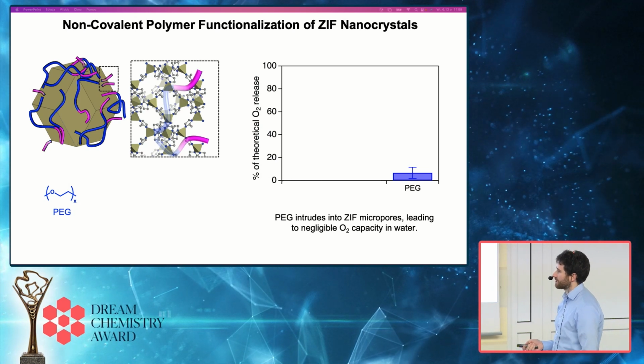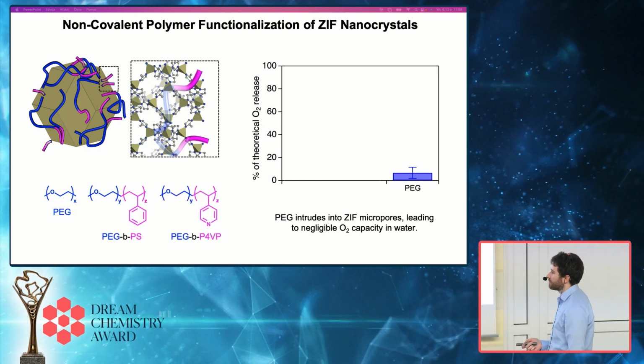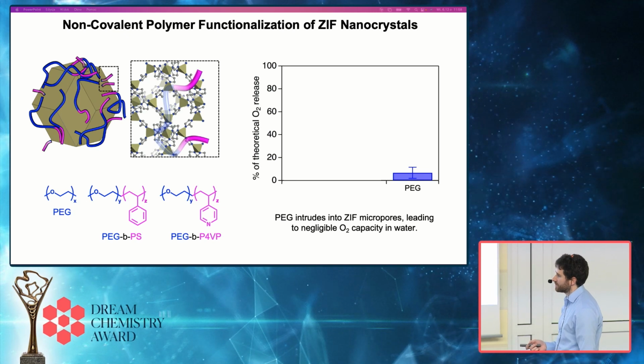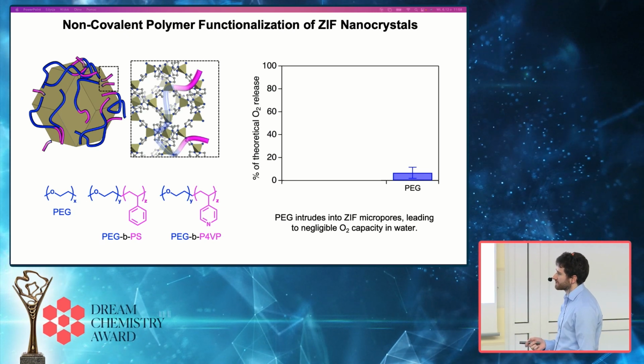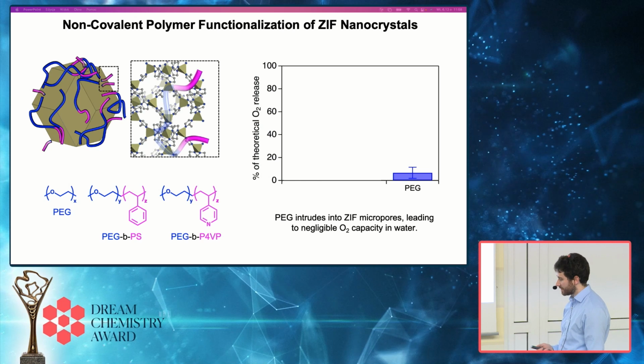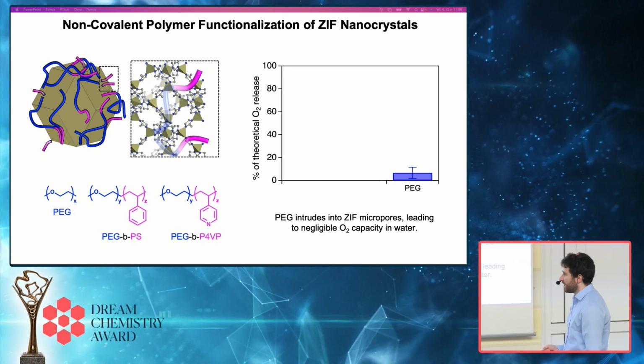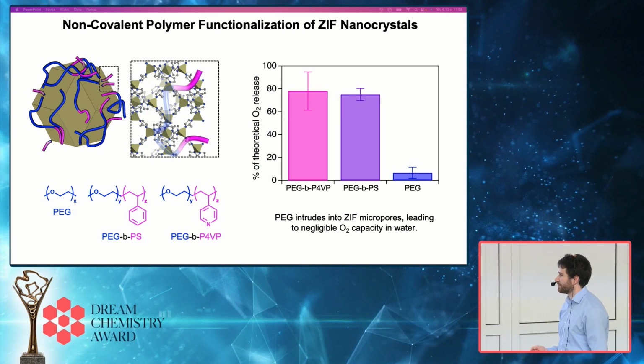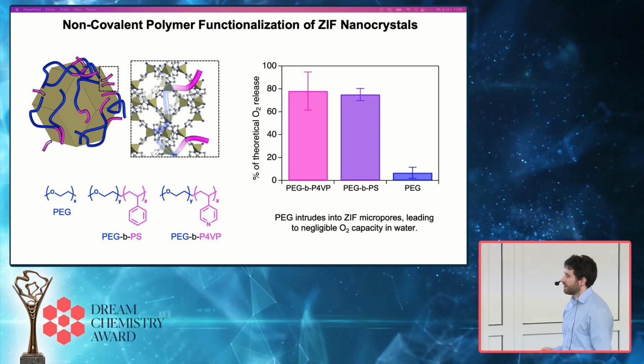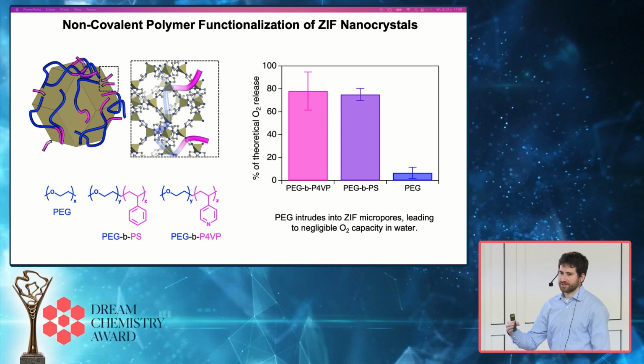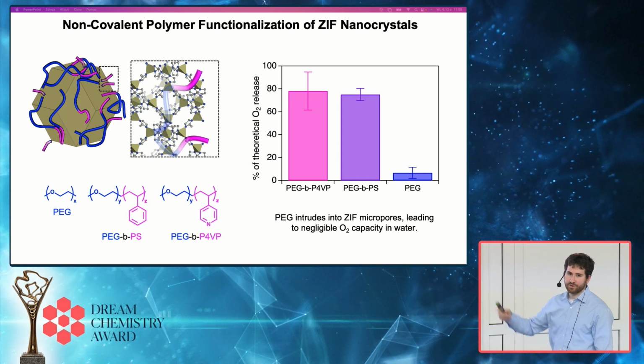So Chris, a postdoc in my group, looked at different block copolymers that can still contain PEG, but contain much more sterically bulky blocks, including polystyrene and poly-4-vinyl pyridine. And what he found is that with certain block copolymers, particularly ones that are quite bulky, we can actually preserve a lot of the porosity of our particles, even with the same amount of PEG present.